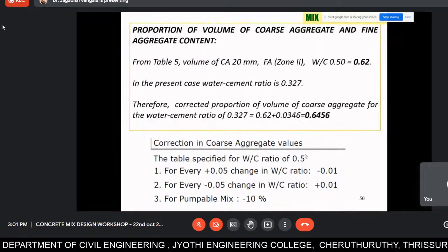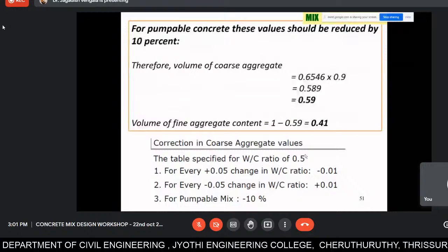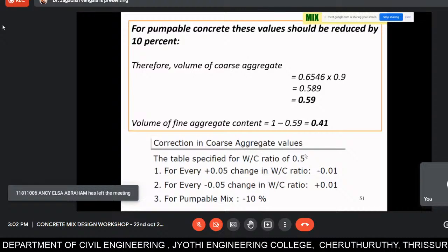But ours is a pumpable mix. Again, there is one more clause for correcting coarse aggregate. For a pumpable mix, you have to reduce the coarse aggregate by 10%. So 0.64 will become 0.59 because you're reducing 10%. Because when you're pumping, too many aggregates should not be there because it gets blocked. So that is why for pumpable concrete, they reduce coarse aggregate by 10%. So the coarse aggregate content is 0.59, and 1 minus 0.59, the remaining, is your fine aggregate, that is 0.41.